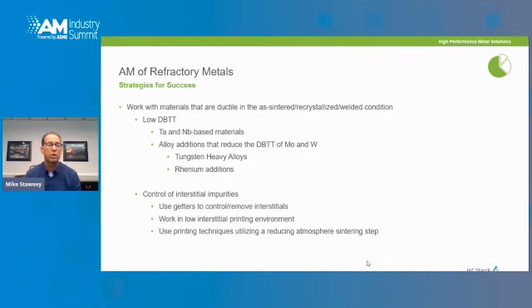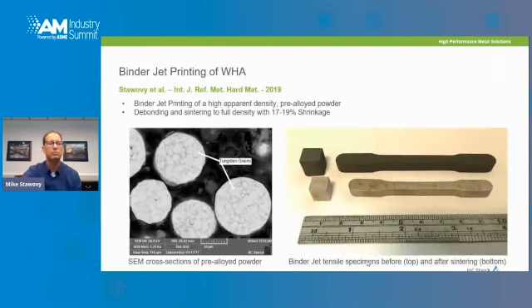You definitely want to work in a low interstitial printing environment. So do everything you can to minimize the oxygen within your printing chamber, whether that's working under vacuum or just really good low oxygen content inert gas. And then if you're using a post-process sintering step, utilize a reducing atmosphere in that sintering step to try and minimize these interstitials.